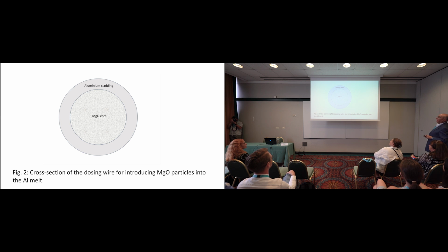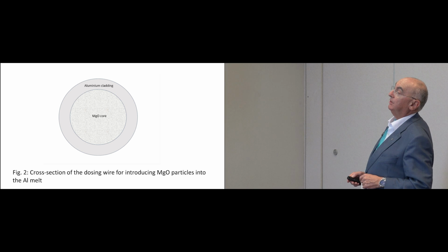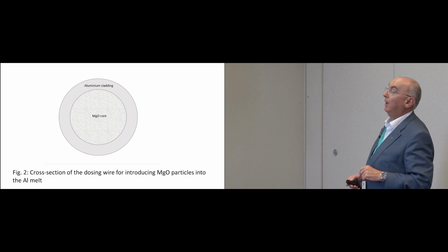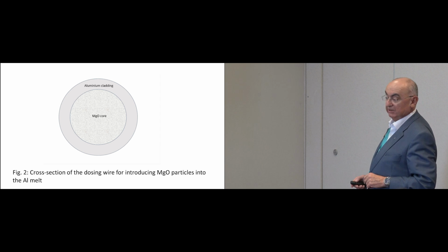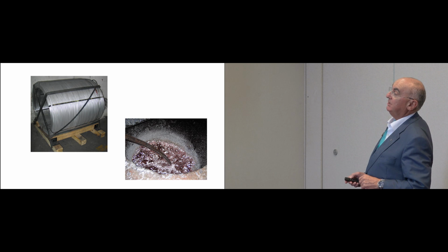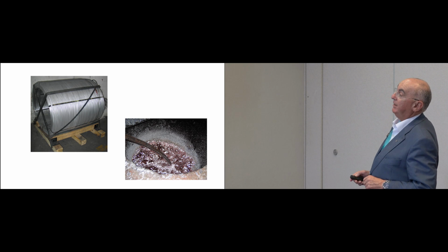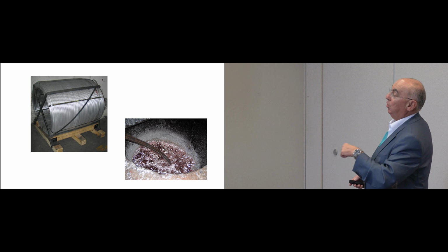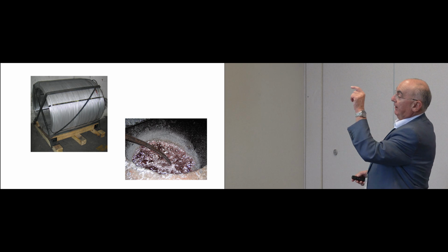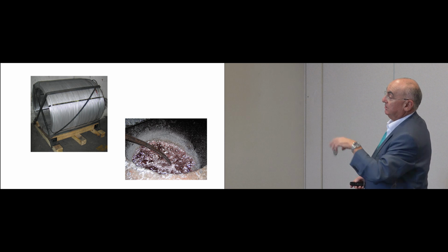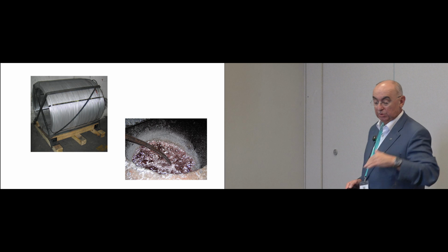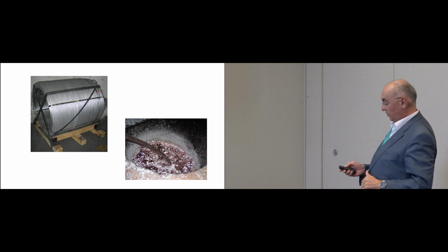We use, we call that dosing wire. The idea was to put magnesium oxide powder into the core of an aluminum tube. We found also that this is a very good way of alloying some alloying elements in aluminum melt. And you will see here, we produce this wire, means that you have cladding of aluminum, and in the core, it is magnesium oxide. And what you see here is a vortex of molten aluminum, so you can introduce magnesium oxide particles directly to the vortex.